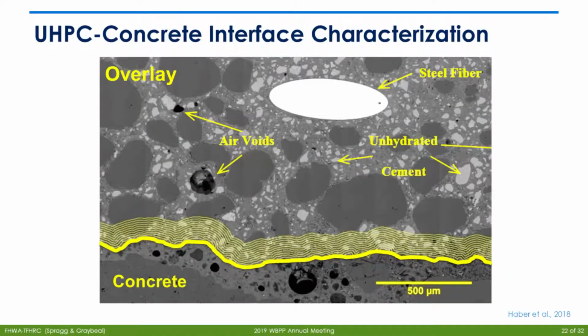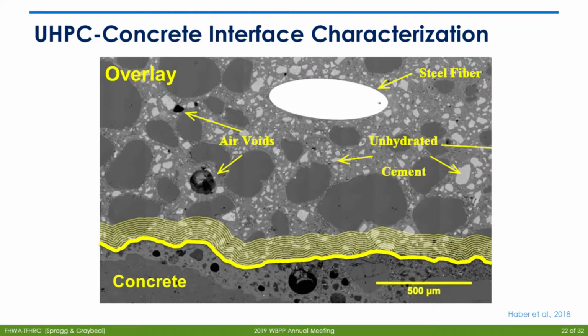To give you an idea, I don't know if anybody has ever had the opportunity to look at concrete under an SEM. This is kind of what it looks like. So you would have your substrate concrete, right? The round black portions in the substrate concrete are the air entrainment that was in your in-place bridge deck. And then the UHPC that was put on top of it. So the interface there is the bright yellow line, and along that interface we measured hydration products as it extended into the UHPC.